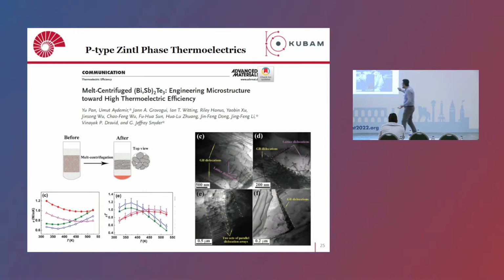And we saw that in bismuth antimony telluride, you can have a lot of ordered grain boundaries, and within the grains, we have a lot of lattice dislocations. You can see that as lattice dislocation networks or regular lattice dislocations. And this lowered the thermal conductivity substantially.